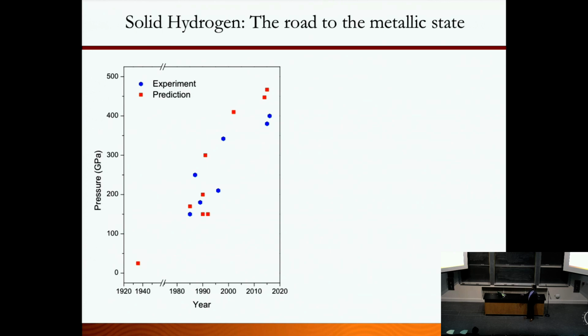So here I just plot the year against the metallization pressure. This is where it was first predicted. The red squares are predicted, and the blue ones are the experimental observations. At 25 GPa they got the density roughly correct, but people achieved it and didn't see any metallization. Every time experimentalists get to a pressure that was predicted, nothing happens and theories change the pressure. So it keeps going up and up, and this is where roughly they stand.